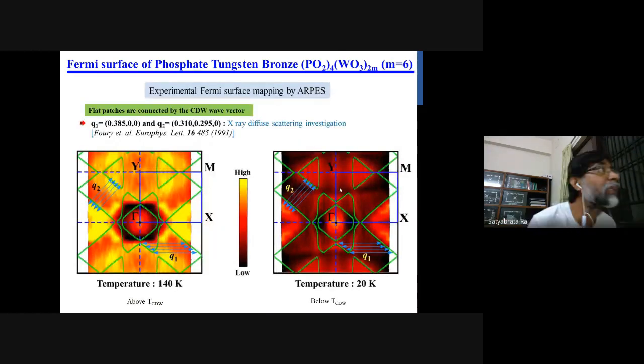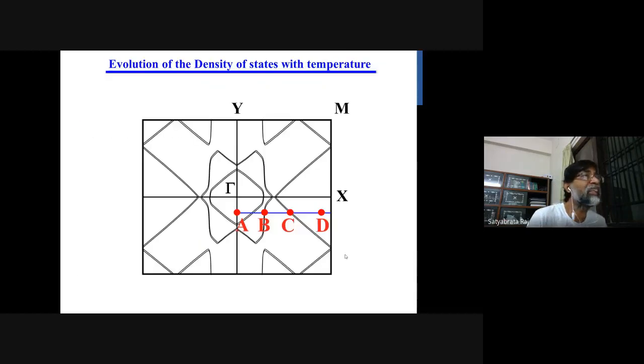And now we have taken the charge density wave vectors from the scattering experiment. These are Q1 and Q2 because of the two anomalies, and we have matched them with the flat patches, and we can see that at low temperature those patches have reduced density of states. That means the Q vectors, Q2 and Q1, remove density of states from this patch of the Fermi surface.